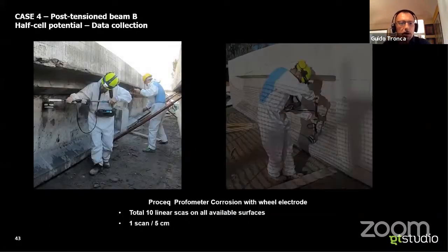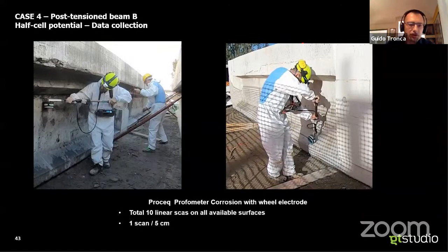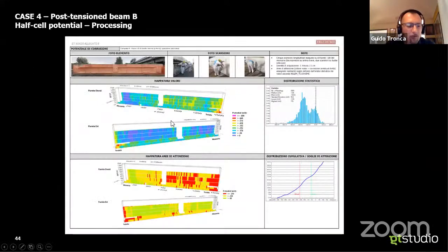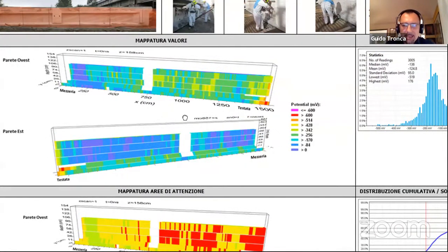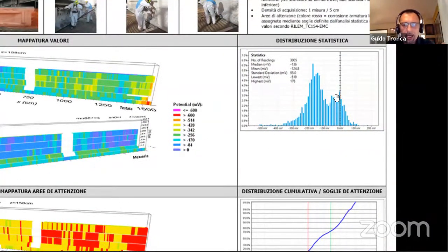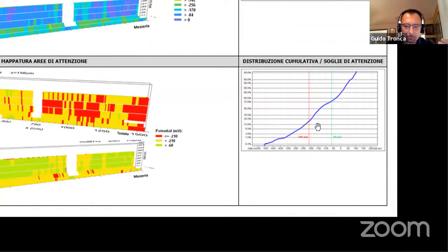Of course, the electrical methods were also requested, and in this case, the ease of accessibility allowed us to actually provide a full mapping of all the surfaces, vertical and inclined surfaces of both sides, providing us a richer database, basically. This is a little bit more textbook curve. You can somehow clearly see the two bells actually corresponding to lower, more negative potential areas corroding, differentiating from areas with higher potential, very unlikely to be corroding,